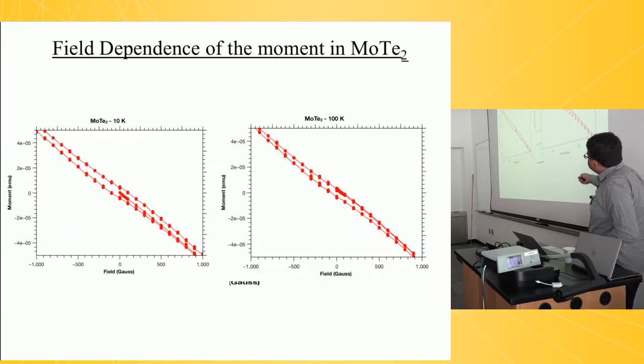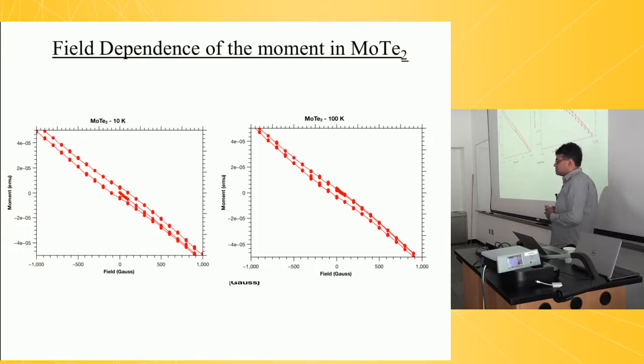And you can sit at the lowest temperature, and you can do a hysteresis loop. This hysteresis loop looks really funny because there's a big diamagnetic signal also in these materials. And so the diamagnetic signal gives you this overall line. If you subtract this line, you'll see a fairly nice hysteresis loop in these materials.